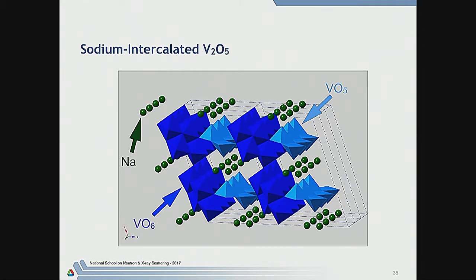But anyway, this is sodium intercalated V2O5, and it turns out that if you put in enough sodium, the V2O5 layers produce this rather buckled structure of pyramids and octahedra. But the sodium ions form these simple ladders. Okay? And if you do powder diffraction on this, you can determine the average structure, and from the average structure you can tell that the average occupation of each of these sites is about 50%. But that's all you can tell. Okay? So that sodium sub-ladder is occupied, you don't know how.